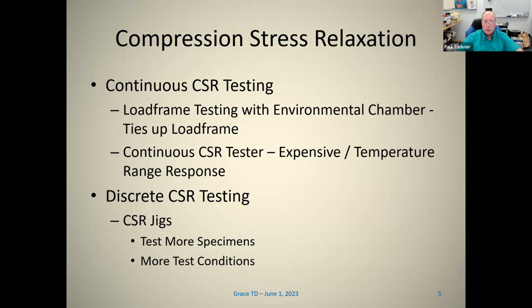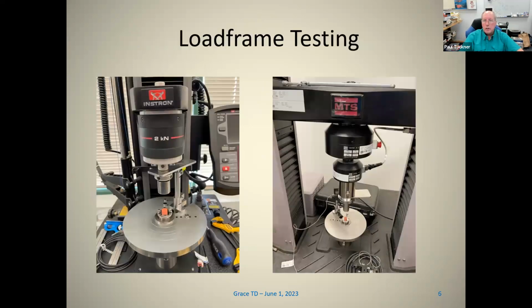And then you have discrete CSR jigs where you put a specimen inside a jig and test them at specific intervals using different techniques to note how that sealing force changes as a function of time. One advantage of discrete jigs is that you can test more specimens under more conditions compared to other methods.